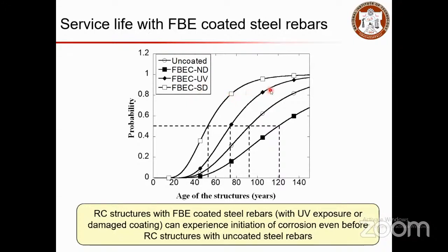When you have surface damage and ultraviolet exposure, the performance is going to be less compared to your uncoated bar itself. The probability of failure with respect to the age of the structure will be more when you have damaged or exposed epoxy coated rebars. So the rebars with coating will perform better only when you take care of them properly with no damage. When you can give proper control or care to a rebar, then you can go with epoxy coated rebar. If you cannot take care of it, then it's better not to use it, and you can go with the conventional rebar, so that the consequence will be less compared to the consequences of using rebar with damages.